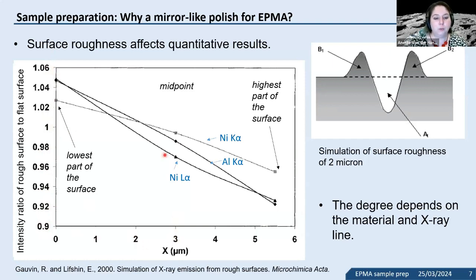3 is supposed to be the relative midpoint, where it's the same as the polished surface, and this would be a topographic high, and this would be a topographic low. Here are examples for a nickel K alpha, aluminum K alpha, and a nickel L alpha line. As you can see, in a material that contains nickel and aluminum, it depends on what X-ray line you analyze, but also what element. You can lose up to 8% of your intensities just by having a final polish of 2 microns.